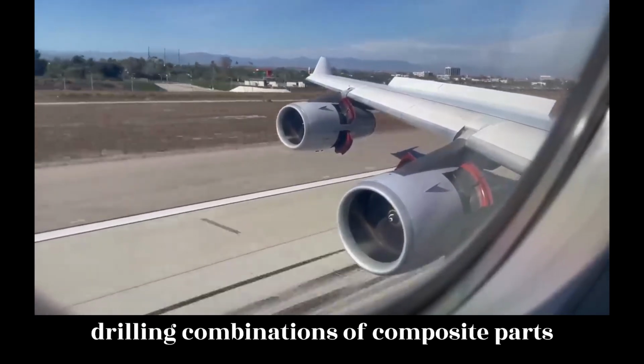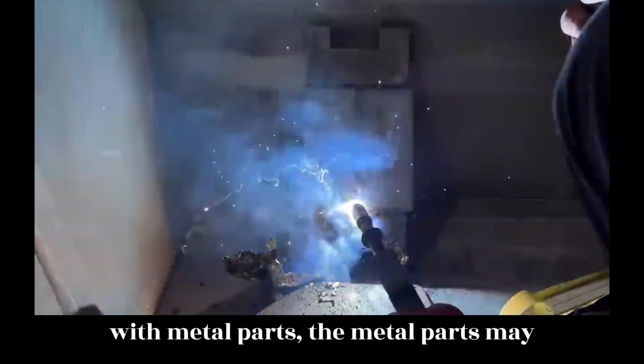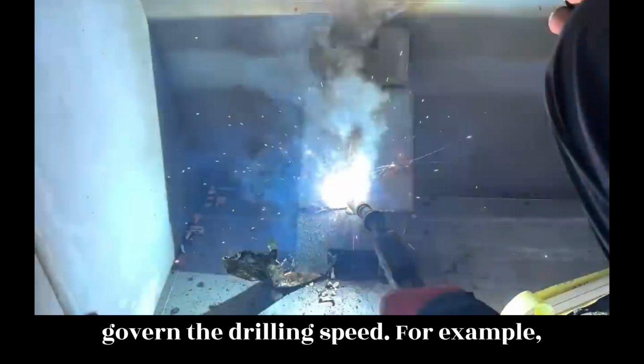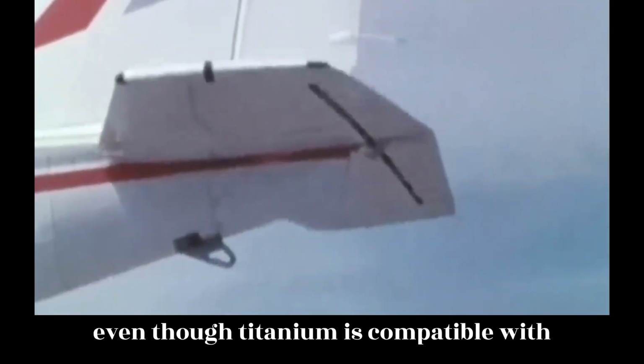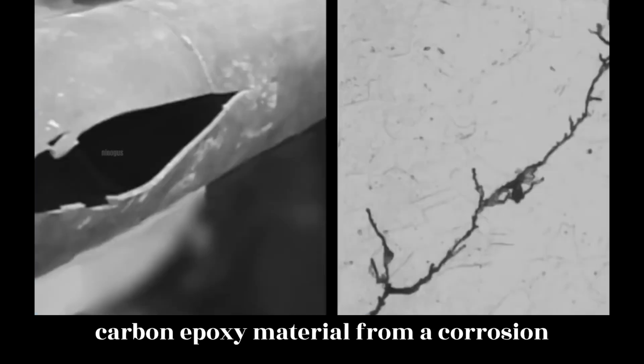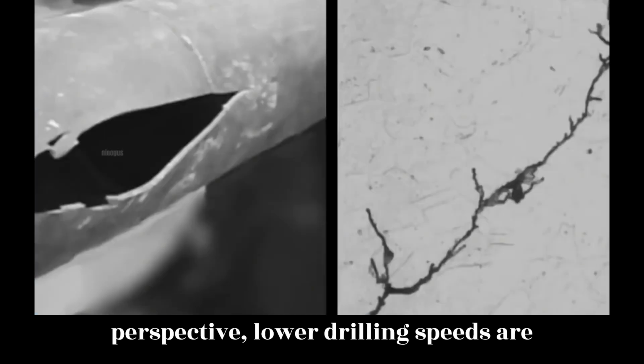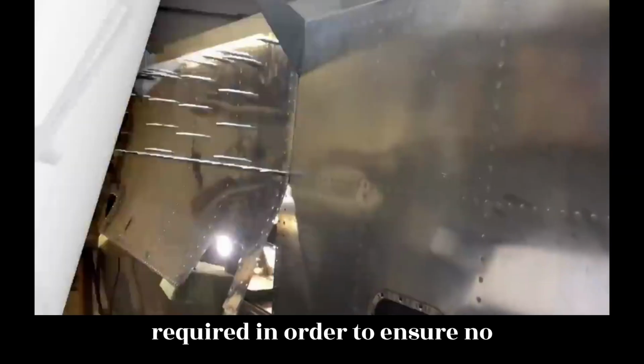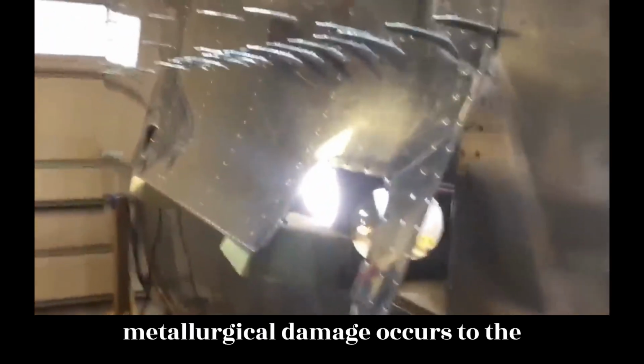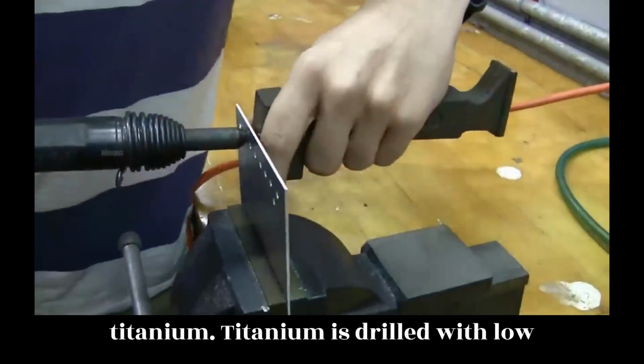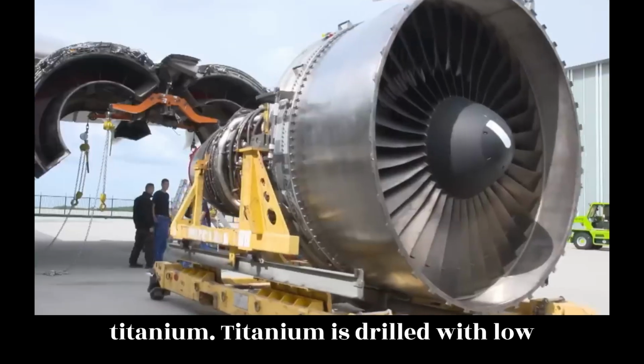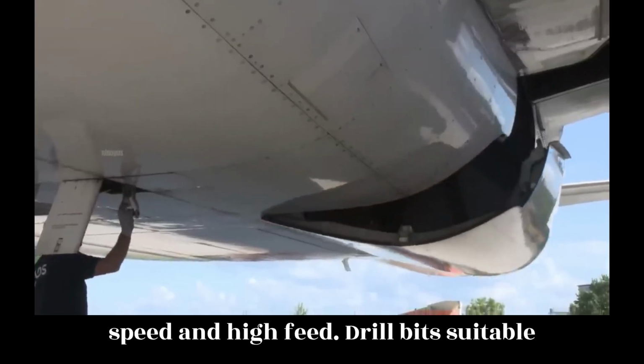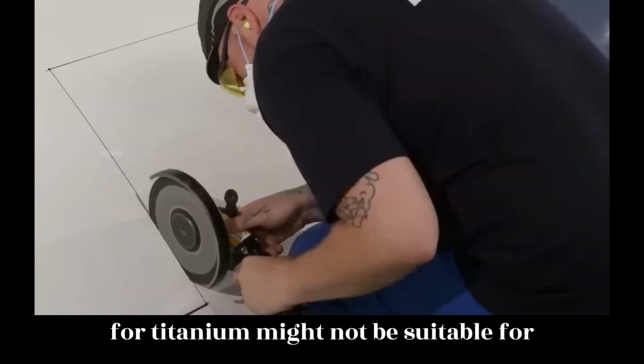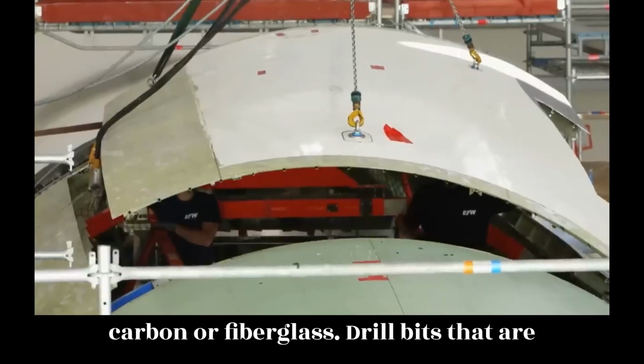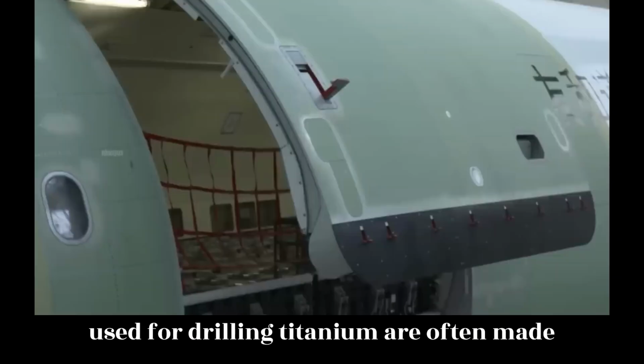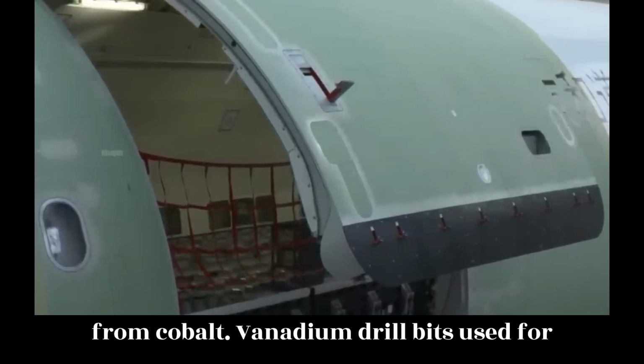When drilling combinations of composite parts with metal parts, the metal parts may govern the drilling speed. For example, even though titanium is compatible with carbon/epoxy material from a corrosion perspective, lower drilling speeds are required in order to ensure no metallurgical damage occurs to the titanium. Titanium is drilled with low speed and high feed. Drill bits suitable for titanium might not be suitable for carbon or fiberglass. Drill bits that are used for drilling titanium are often made from cobalt vanadium.